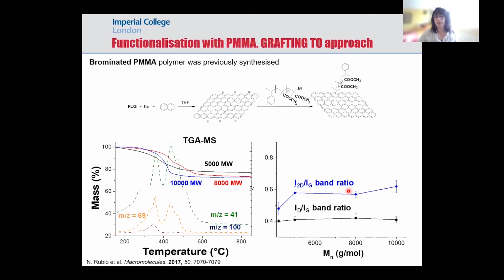Looking at the approach where we previously synthesized the polymer and then attached it directly on the graphene, in general we were seeing lower mass loss values, meaning that we were not able to attach such a big amount of PMMA as with the previous approach. And from the Raman experiments, from the D to G ratio, we didn't observe a very significant difference between different molecular weights. Probably, as we can see from TGA, we are having more or less a similar amount of polymer grafted on the surface.